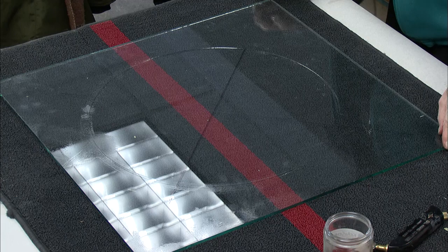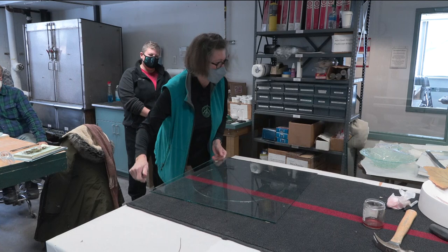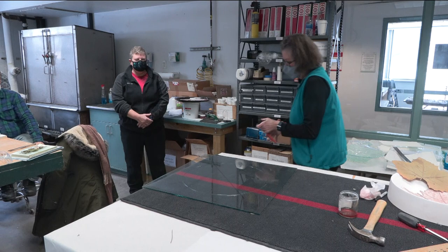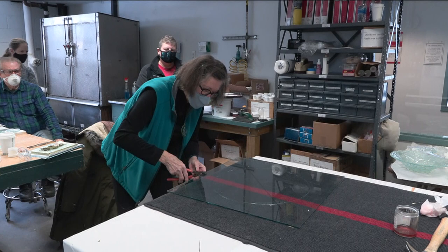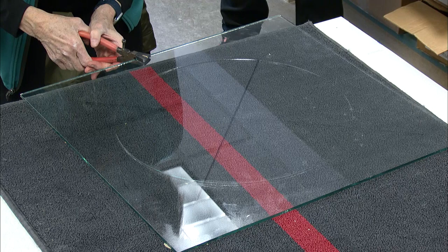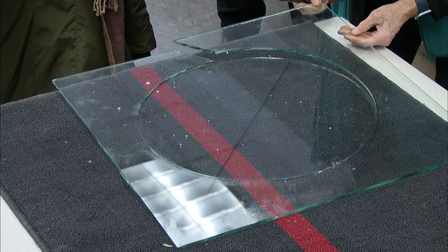with Bullseye and 96 that are thinner, often you can just start doing that and it breaks free. But float glass is a lot stiffer, so I like to run the score a little bit around. And you use your pliers with a fulcrum and line it up in the direction of your score. Okay, and just hit it lightly. So I hit it lightly, because if you do it hard, it might just keep going. Now, look at that. I can almost get this out without even running another score, but I'm going to do it anyway.